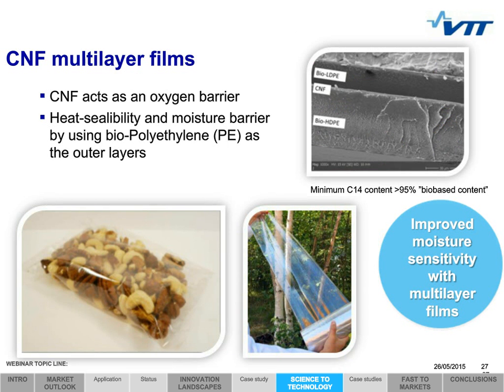Firstly, we have created multi-layer films containing CNF as the middle layer, acting as the oxygen barrier. The electron microscope image in the upper right-hand corner reveals the structure of this film and shows that the thin CNF layer is wedged between the two polyethylene layers. The thickness of the CNF layer is only a few micrometers. When using bio-based polyethylene as the outer layers, we have obtained heat sealability and moisture barrier for the transparent film structure, enabling the use of the film for packaging of dry foods, such as nuts.